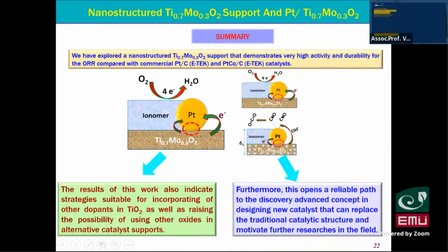We think that this result also indicates the trajectory suitable for incorporating other dopants into titanium oxide, as well as raising the possibility of using other oxides as alternative catalyst supports. This will open new paths related to the mechanism I mentioned, due to the electron transfer from the support to the catalyst.